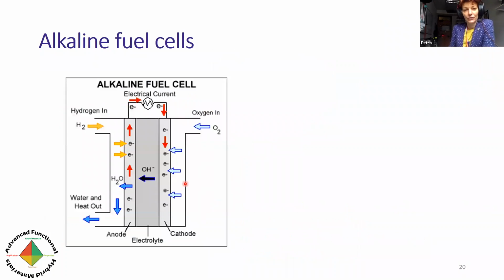So there is an alternative, of course. Some other metals such as iron or nickel are quite good electrocatalysts when it comes to, for example, hydrogen oxidation or oxygen reduction. However, of course, they're not stable in acidic media. So if we could go from acidic media to alkaline media, that would be a great advantage in terms of cost and sustainability of the fuel cell systems. So this is just to demonstrate a little bit how it works. You still have obviously the same electrode reactions on both sides. What would be different is the electrolyte and the membrane in between. So instead of the protons going from the anode to the cathode, you would have hydroxide ions migrating from the cathode to the anode side, where the hydroxide ions can react with the oxidized hydrogen.